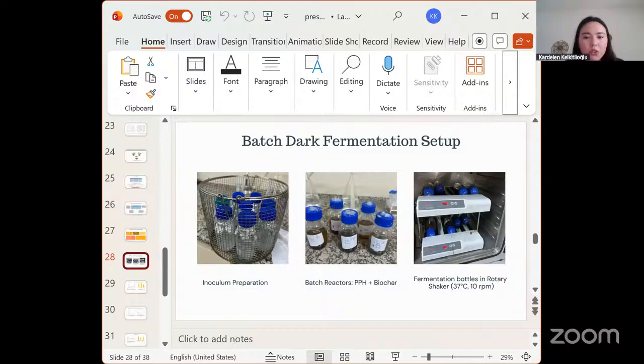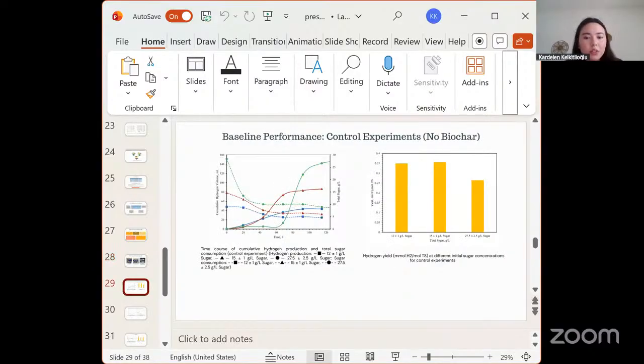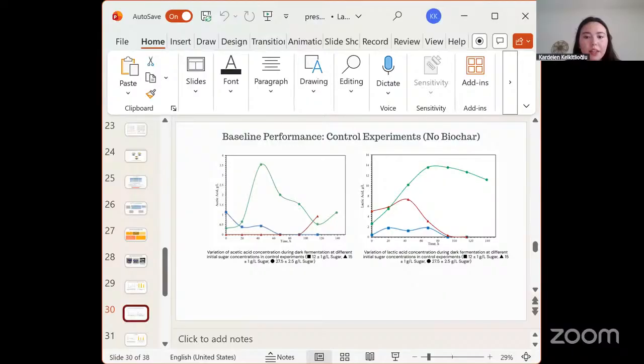As you can see in these photos, the experiments were carried out in anaerobic serum bottles inside a rotary shaker to ensure uniform conditions across all trials. In our control runs without biochar, low sugar loading produced hydrogen efficiently, but at the highest loading, despite high sugar consumption, yield dropped to just 0.26 moles of hydrogen per mole of total sugar. At high sugar loading, lactic acid accumulated massively and was never depleted, while acetic acid was suppressed.